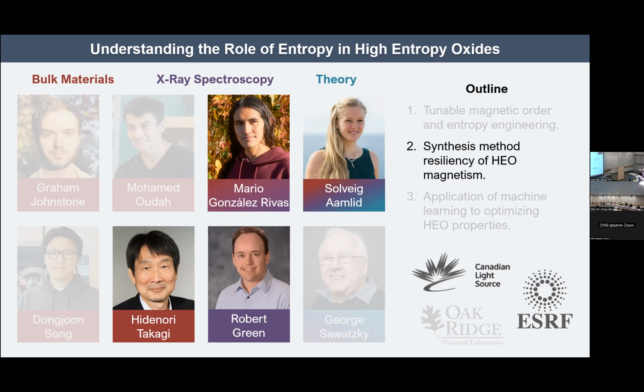Okay, as I had mentioned before, my background is in quantum magnetism, and actually we got a taste of this in JP's talk, which is that a common plight in any quantum state of matter is how disorder is going to affect that fragile state. This is very different than that, obviously. We're deliberately introducing disorder, but the question is, how perfect is that disorder? My intuition was that just as it is impossible to make a perfectly ordered material, it should be equally impossible to make a perfectly disordered material. And synthetic conditions should matter greatly.